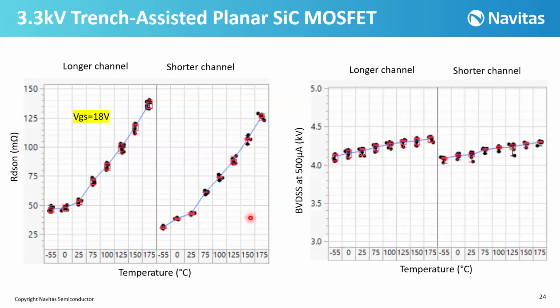Here's the breakdown voltage for both the shorter channel and longer channel at 500 microamps from -55 to a high temperature of 175 degrees C. Again, we have a little bit lower breakdown voltage in the shorter channel compared to the longer channel. So obviously, if you compare the shorter channel and longer channel regarding the forward characteristics and the breakdown or reverse characteristics, we can see that we have a lower RDS on and a little bit lower breakdown voltage in the shorter channel. However, even for the shorter channel, the breakdown voltage at room temperature, which is 25 degrees C, is around 4.15 kilovolt for the 3.3 kilovolt class. So it is more than enough for these products. And again, the breakdown voltage for both of them increases from low temperature to high temperature, for both the longer and shorter channel.